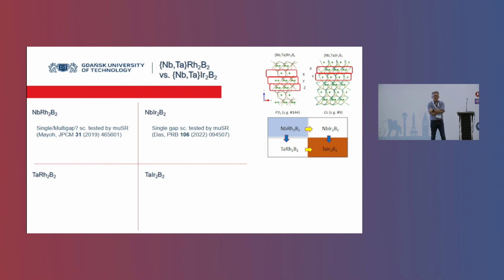Those 4 new superconductors, Bob Cava and also my lab reported or just discovered. Niobium rhodium 2 B2, tantalum rhodium 2 B2, that's the chiral structure. Niobium iridium 2 B2, tantalum iridium 2 B2, this is a monoclinic crystal structure type. For niobium rhodium 2 B2, the group from Warwick University in the UK already published a paper showing that there is a single or maybe multi-gap, that's the conclusion, tested by muon spectroscopy.